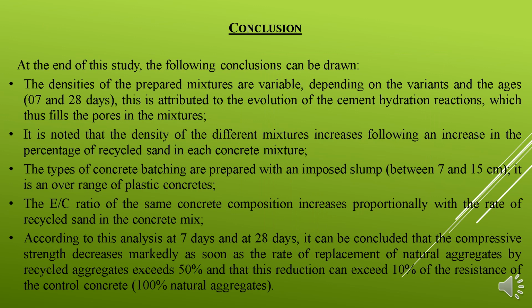In the last part, I will conclude my presentation. At the end of the study, the following conclusions can be drawn. The densities of the prepared mixtures are variable depending on the variation and the age, 7 and 28 days. It is noted that the density of the different mixtures increases with an increase in the percentage of recycled sand in each concrete mixture. The types of concrete batching are prepared with an imposed slump between 7 and 15 cm. The E/C ratio of the same concrete composition increases proportionally with the rate of recycled sand in the concrete mix.